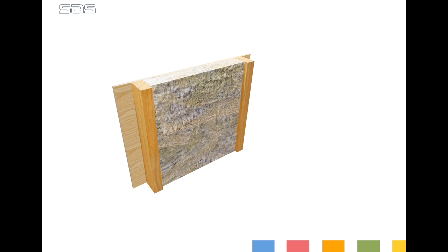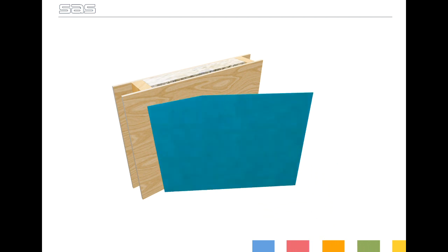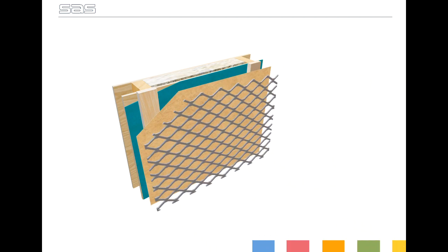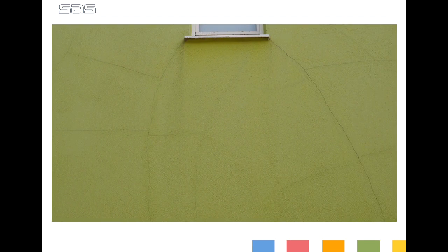So how do we apply render to timber frame without building an additional masonry wall? Traditionally, battens would be fixed through the OSB and back to the frame, and an EML — expanded metal lath — with building paper would be fixed to the studs over the entirety of the frame. A render would then normally be applied to the EML as a two-coat system and finished as desired. While this method is still used today, it is declining in popularity, as it's becoming increasingly apparent that it has some potential pitfalls. Thermal expansion and contraction, coupled with movement seen in timber frame construction, can cause the render to crack and, in worst cases, delaminate from the surface. If we have a look at these photos, you can see exactly that's happened.